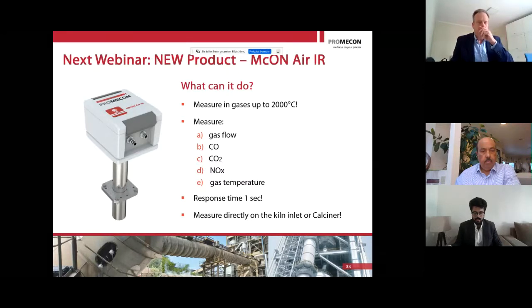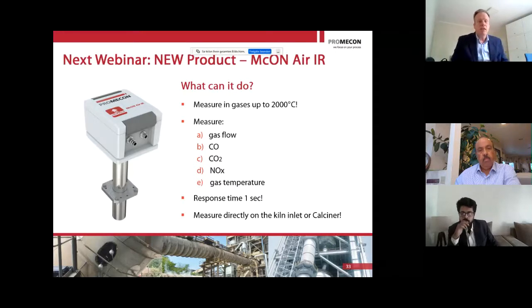It will melt, right? So we developed this state-of-the-art infrared sensor that looks at the light in the process and that has two sensors and correlates the light. And by this light correlation, we can also measure the gas velocity up to 2000 degrees Celsius. And since we are looking into the infrared, we also have equipped the sensor with technology that allows us to measure not only gas flow, but also carbon monoxide, carbon dioxide, as well as NOx and gas temperature.